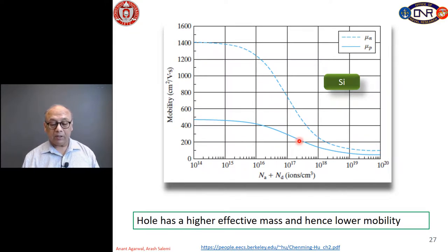And you can see that for very, very low doped samples, the mobility is high because that's dominated by phonon scattering. So in this case, electron mobility for very low doped material is roughly 1400 centimeters square per volt second, and holes have a lower mobility in general in many semiconductors because holes have a higher effective mass, and therefore in silicon, very low doped material, the hole mobility is of the order of about 500 centimeters square per volt second.